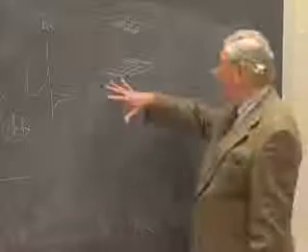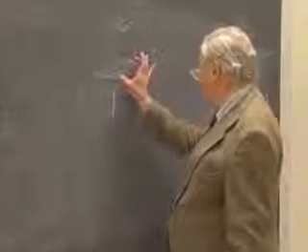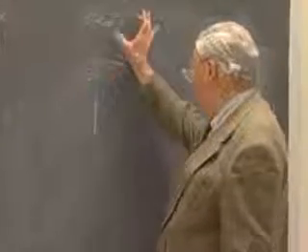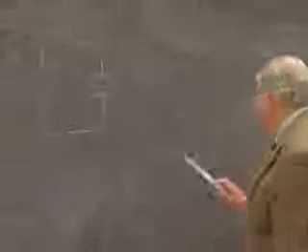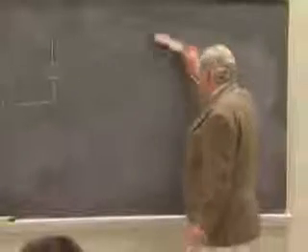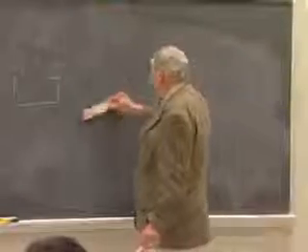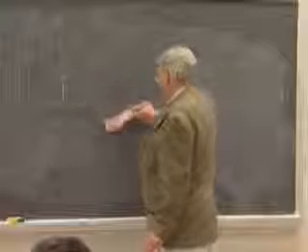And you can determine for a particular frequency, if this is the 1.5 wavelengths along a dimension that you know, you can again find the piezoelectric moduli. So there are lots of ways of detecting this effect. But when you have a single crystal, you've got to really look at this as a function of direction to be absolutely sure.